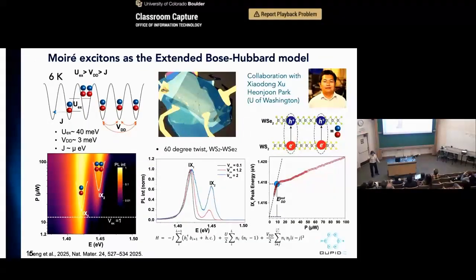Okay. So in order for us to image these exciton phases, we have a collaboration with Professor Xiaodong Xu's group on this twisted bilayer tungsten sulfide, tungsten selenide system. The reason is that for this measurement to be successful, you need the material quality to be very, very high, because you don't want other energy scales coming into play when you're trying to look at U versus J. And Xiaodong's group by far makes the best samples. This is a sample of twisted tungsten sulfide, tungsten selenide, where the lowest exciton state is an interlayer exciton, where the hole resides on the tungsten selenide layer and the electron resides in the tungsten sulfide layer.